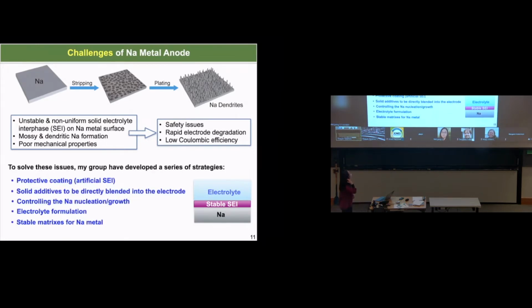So during the past 7 years, my group has developed a series of strategies. We have developed some protective coating, which we call an artificial SEI layer, to directly coat on the sodium metal surface. In this case, we can improve the stability of the sodium metal electrode over long-term cycling, the stripping and plating process. Another thing is we also developed some solid additive. We can directly blend it with sodium to improve the mechanical properties and solve the poor mechanical issue of the sodium metal anode. And then we also try to control the sodium nucleation growth to manipulate the sodium plating process to achieve